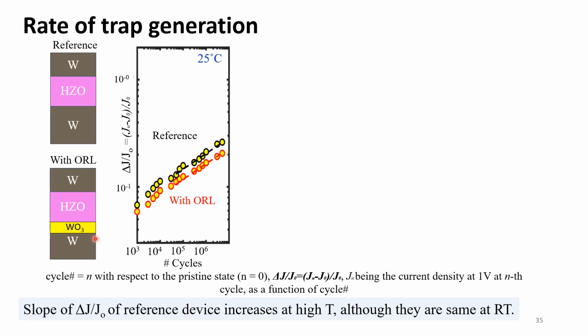Here you can see a plot where the y-axis is del J over J naught and the x-axis is the number of cycles. Del J over J naught is the difference between the leakage coming from a certain number of cycles and the pristine leakage, divided by the pristine leakage. So the slope of this plot is a measure of trap generation rate. The black curve is coming from the reference device and the red curve is coming from the ORL device. This is for the measurement done at 25 degrees Celsius. You can see the slope over here is very similar for both the devices.